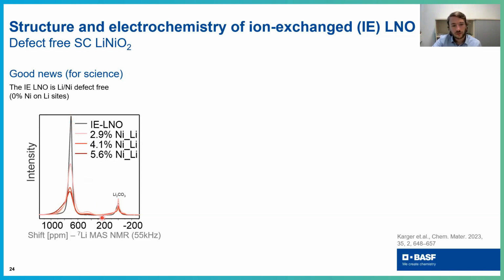And an interesting feature here is this shoulder around 480 ppm, which is indicative for nickel 2+ around lithium, and basically you do not see this signal for our ion exchange sample at all. And this is good news. We have really managed to make ion exchanged lithium nickel oxide, which has no nickel on lithium sites. Yeah, and this is, I think, for the first time. I have not seen such a material before in the literature, which is very good.